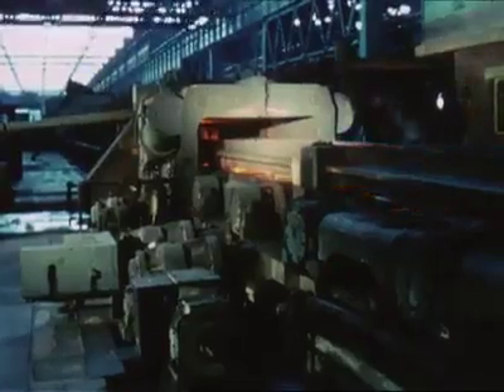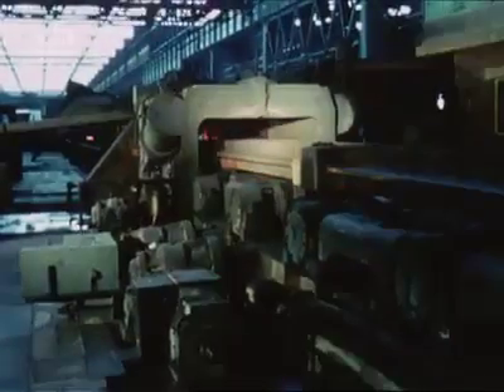The ingot is progressively reduced in cross-section during rolling, and the resulting bloom is passed along the outgoing roller tables to the continuous hot scarfing machine. For exacting surface quality requirements, the four surfaces of the hot bloom are scarfed simultaneously by means of sets of oxypropane gas burners. The surface metal is removed to a controlled depth up to 1/8 of an inch.